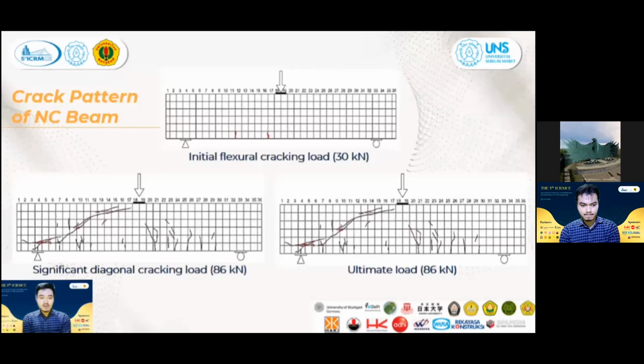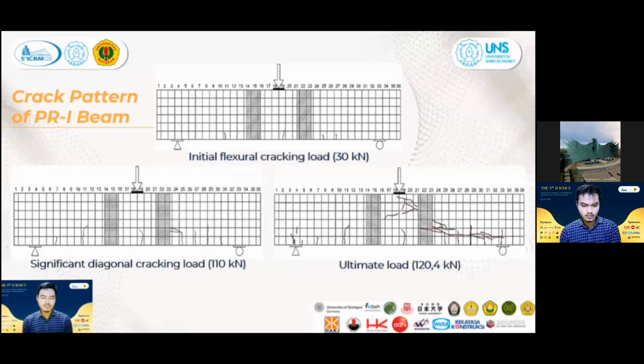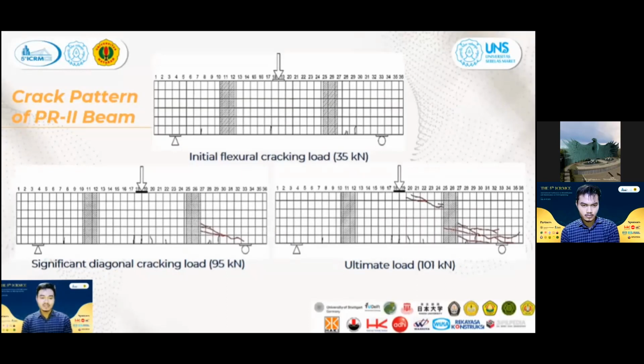And next, crack pattern sketch from NC beam. The flexural cracking capacity was at 30 kN. The significant diagonal cracking load was at 86 kN, and the ultimate load occurs at the same load, 86 kN. The flexural cracking capacity was at 30 kN. The significant diagonal cracking load was at 110 kN, and the ultimate occurs at 120.4 kN. And next, crack pattern sketch from PR2 beams. The flexural cracking capacity was at 35 kN. The significant diagonal cracking load was at 95 kN, and the ultimate load occurs at 101 kN.